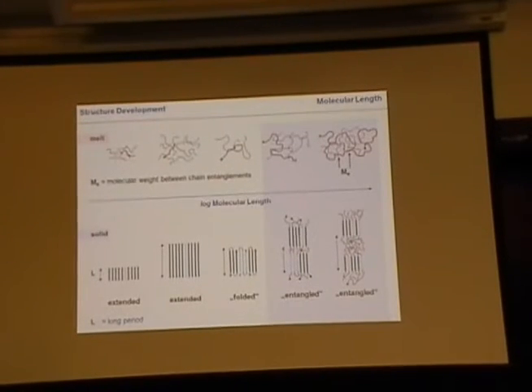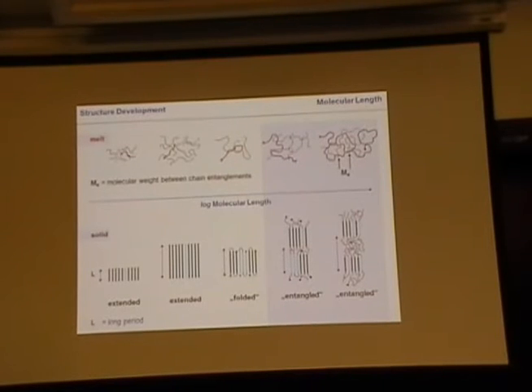In the polymer world, only those, as mentioned, that we call plastics. Those we can plastically deform. Because when we stretch these materials, you stretch out actually this amorphous phase. So the less entanglements you have in this amorphous phase, the more you can stretch this material. These, though, they are very brittle. They nearly will fail on this interface.